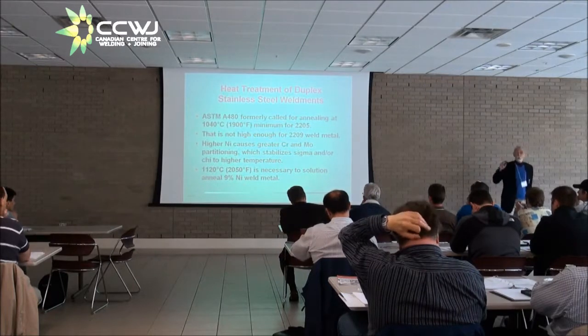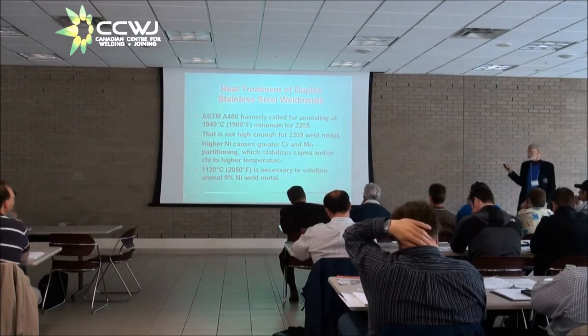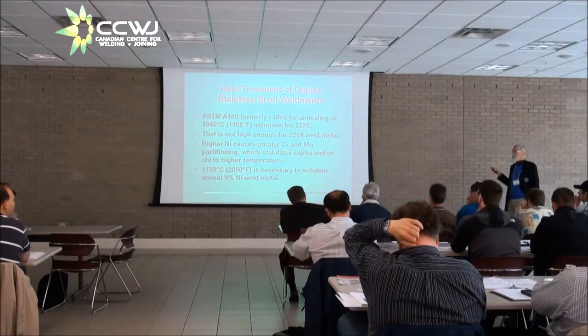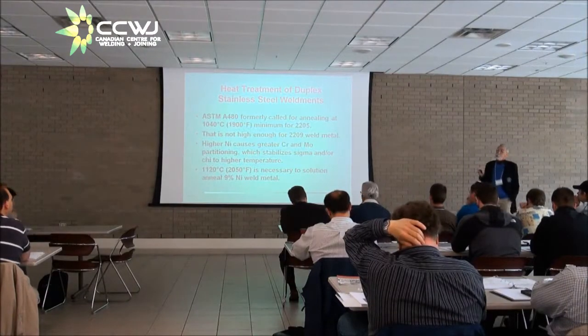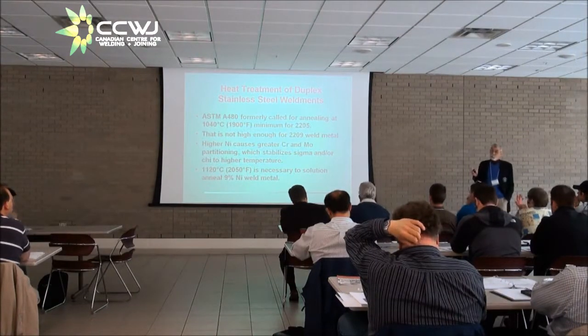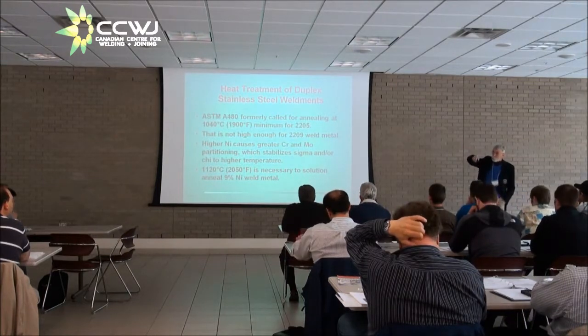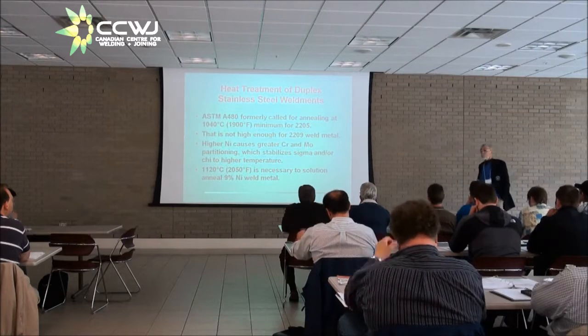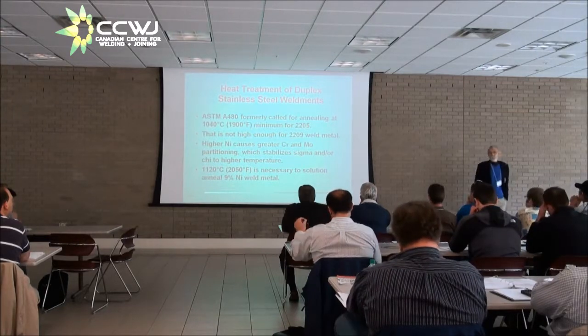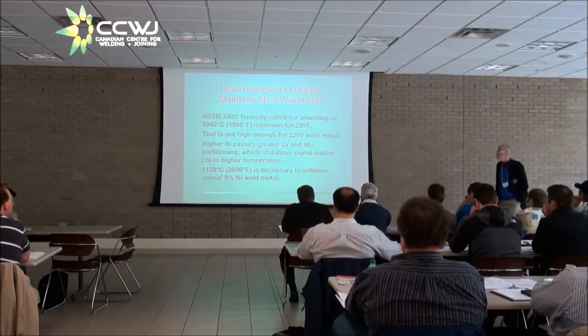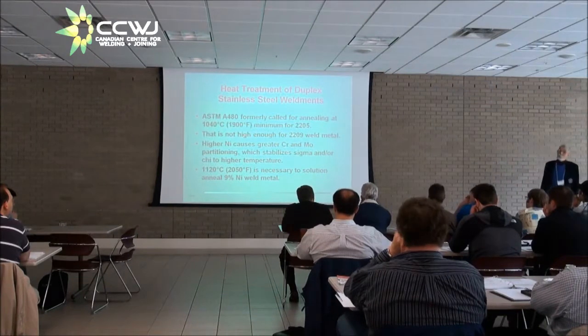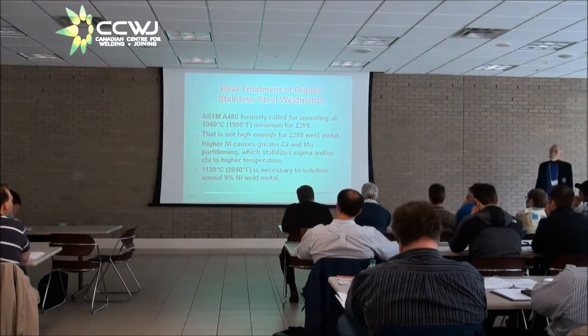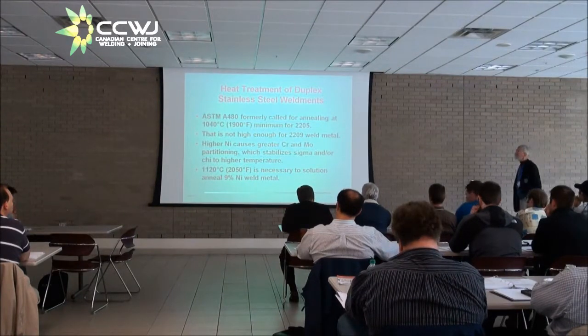Heat treatment of duplex stainless steels, especially when they've been welded, is a little bit of tricky business. Because we're saying, well, you've got a whole temperature range from 400 degrees Celsius up to something over 1050, 1070 degrees C, where bad phases form. Sigma phase, chi phase, and alpha prime.